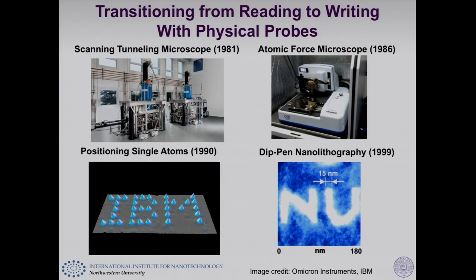With Dip-Pen Nanolithography, we used a variant of the atomic force microscope, which was an instrument that uses a tip to basically feel a surface. It was designed to be a reader, so that you could get a topological map of the surface as you move the tip around and got a contour map of the surface. Very powerful from a surface science standpoint. And we looked at it and said, why couldn't we turn that into a writer? Why couldn't we think of that as a dip pen, or like a quill pen, coat it with molecules of interest, and transfer those molecules to an underlying substrate? And it turns out you can, but you have to know some tricks.